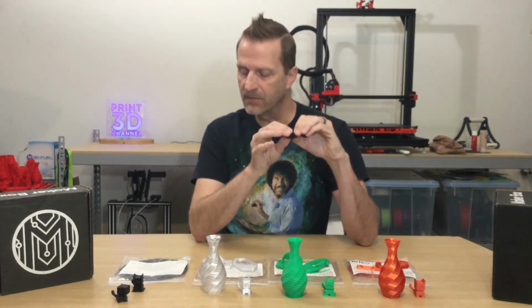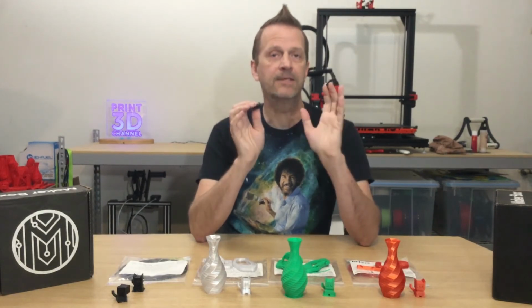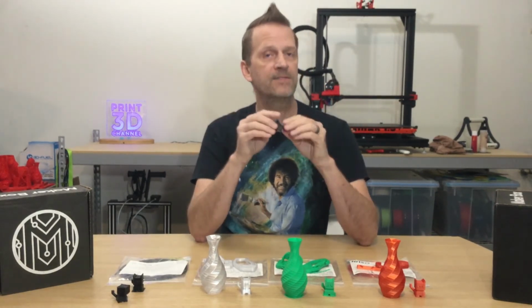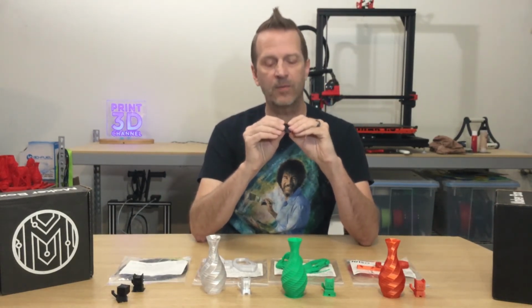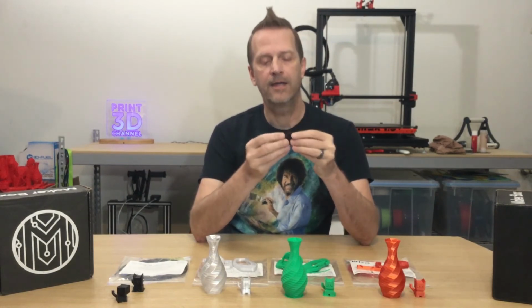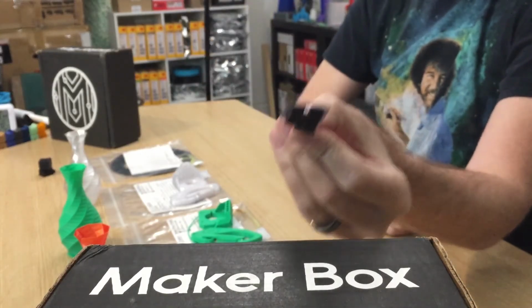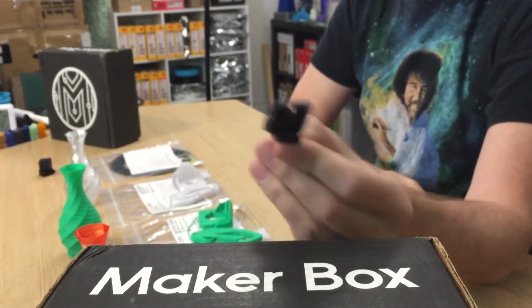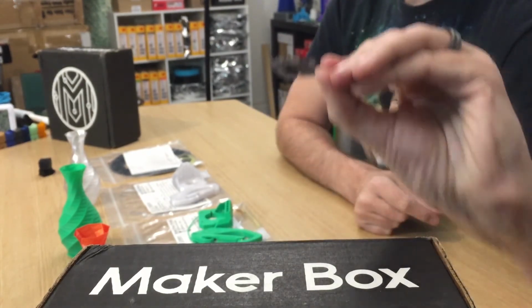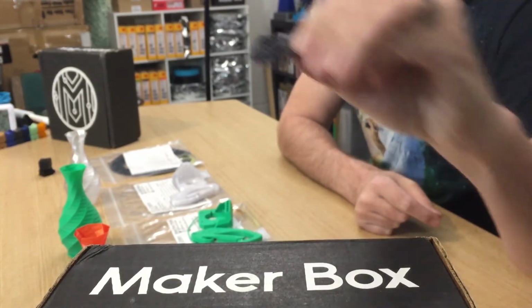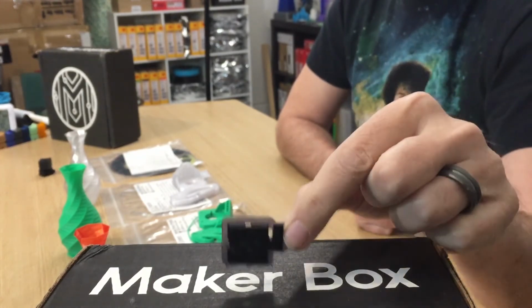So the bed temperature was originally set at 45°C. I moved it up to 55°C, thinking that a little hotter should keep the plastic stuck a little longer. And this one warped off the print bed immediately. I didn't get far at all. I mean, it did its bridging, and the print looks really good too, and that's what stinks. It came off the print bed.